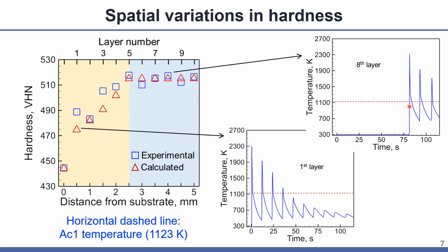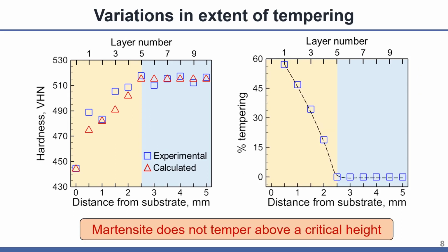However, for the lower layers, for example, for the first layer, the peak temperature did not exceed the AC1 temperature after the deposition of a few subsequent layers. The repeating heating and cooling below the AC1 temperature gradually transformed the martensite into tempered martensite and reduced the hardness. It is evident that with the deposition of layers, the extent of tempering decreased and the hardness increased until a critical layer was reached, beyond which hardness and tempering remain unchanged.